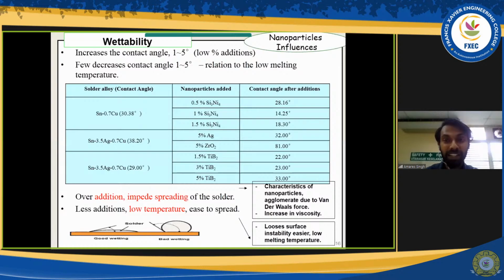So here the weight percentage actually plays a part, because when we try to add more, nanoparticles have a certain character that they will attract to each other if they are a lot. During the melting process, at the edge of the solder is where the high energy is present. So these nanoparticles will be at the high energy area, and if the additions are a lot, they tend to agglomerate. When they gather together, that means the solder will not be easily spread. There's like an impeding item or particles that will not allow the solder to spread properly.